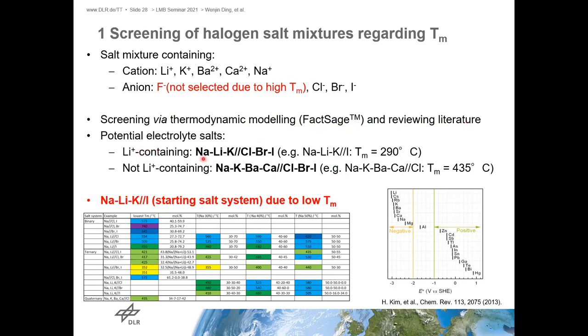We find two groups of low melting temperature salt mixtures for the sodium-based liquid metal batteries. One contains lithium, so it's lithium, sodium, and potassium halide salt mixtures. And another is without lithium. Regarding lithium chloride, maybe it's expensive. So first we study this lithium-containing salt system due to its low melting temperature. It can be lower than 300 degrees C.